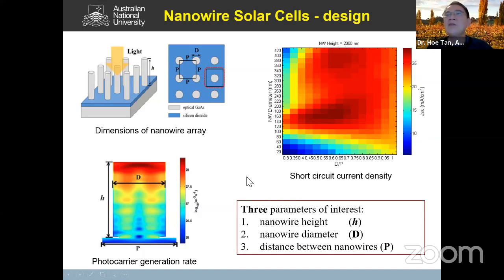And then the next thing, if you want to make a nanowire solar cell, what we did was we optimized the short circuit current density here, okay? As a function of the nanowire diameter and the diameter divided by the pitch ratio, okay?